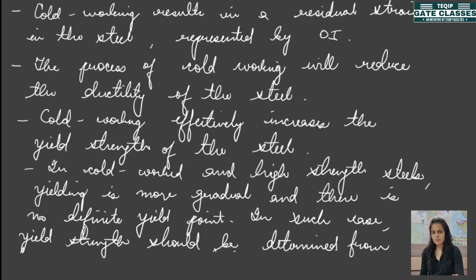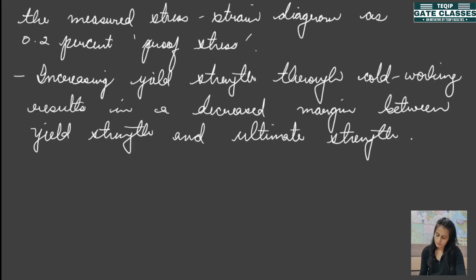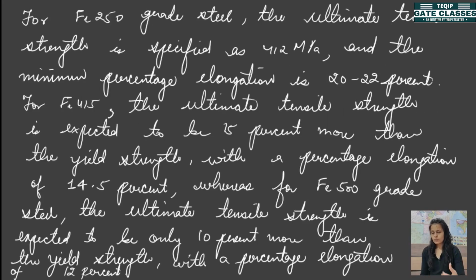Then the yielding will be more gradual and there will be no definite yield point in the stress strain diagram of the steel after cold working. So the yield strength is measured as the 0.2% proof stress. Also, increasing yield strength through cold working results in a decreased margin between the yield strength and the ultimate strength of the steel. Right? To verify that, these are the values for different grades of the steel, that is Fe250, Fe415 and Fe500.